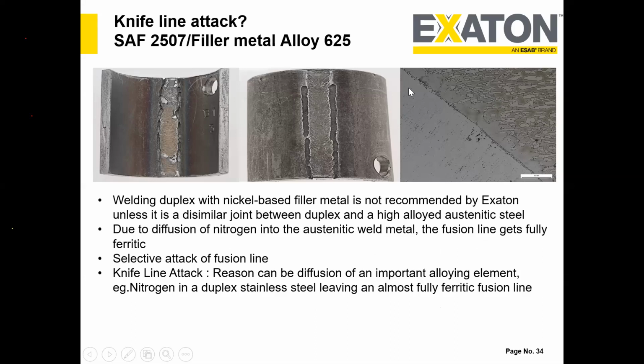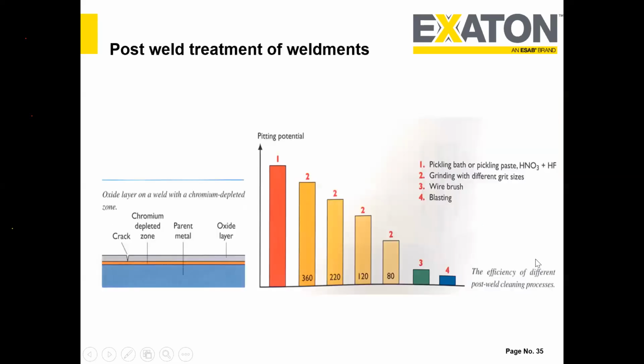So this is the area called UMZ, whereas HAZ is the heat affected zone. UMZ is called the unmixed zone. So it does not mix properly. So we recommend not to use Inconel 625 or nickel-based, basically any filler wire. Now this is the important post weld treatment.